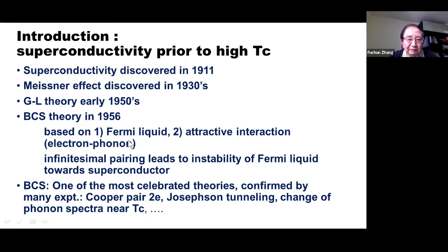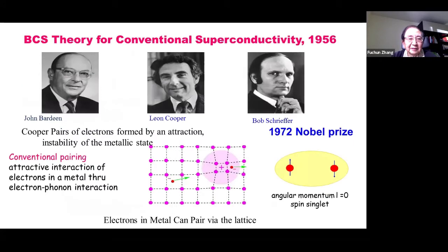Okay. And that BCS theory is based on two things. One is starting from a Fermi liquid. The second is having an attractive interaction. The electron-electron interaction is made attractive by the electron-phonon interaction. And they show that infinitesimal pairing will lead to an instability of the Fermi liquid towards the superconductor. So BCS, as we all agree, is one of the most celebrated theories and is confirmed by many experiments, such as Cooper pair 2e, the Josephson tunneling, and the change of the phonon spectrum near TC.